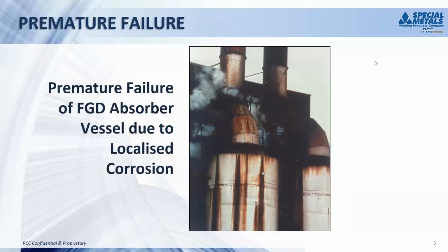The next slide, John. This is an example of what can happen when inadequate materials are used for construction of the system. These are two scrubber vessels that were fabricated from 316L stainless steel. After about a year of service, you can see the result. There's leakage of the material from inside the vessels coming down the outside, so the walls have been completely perforated by corrosion. And you'll also see some smoke up at the top there. That's not supposed to be there. So again, that's the result of leaks caused by perforation of the 316 stainless by corrosion.